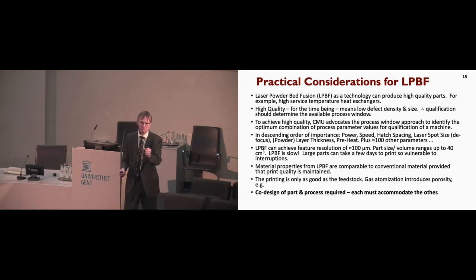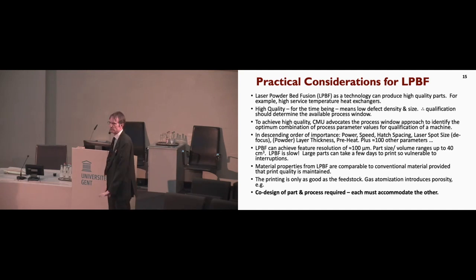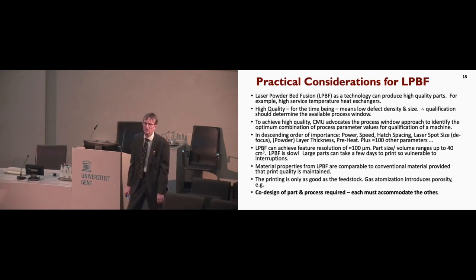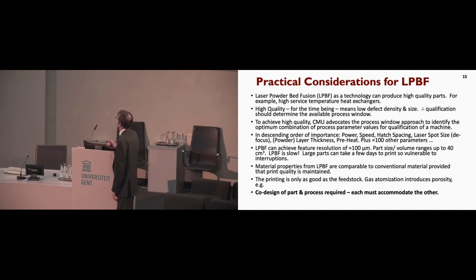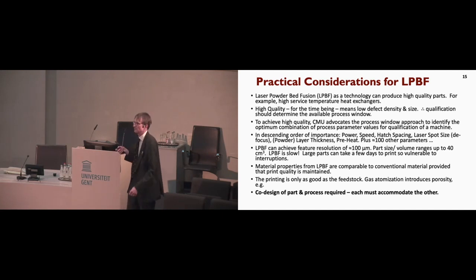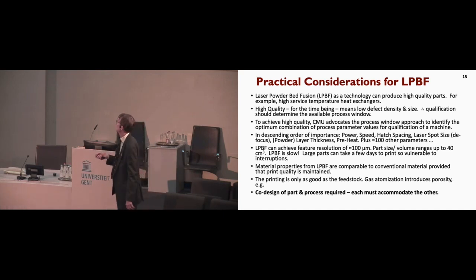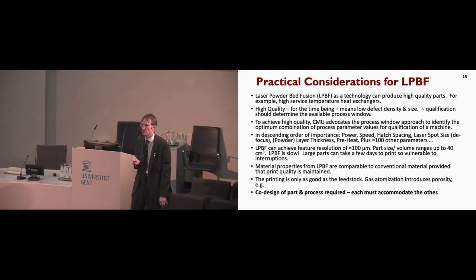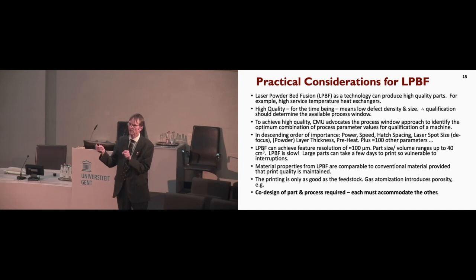Okay, so now I'm going to abruptly change gears, go from low gear to high gear, if you like, and just offer you some more practical thoughts about at least laser powder bed fusion, which at the moment is the dominant technology. It's a technology that basically should be looked at as producing high quality parts. It can do this. And from the perspective of defect content, many of those applications are fatigue sensitive, or maybe they're corrosion sensitive. So the point is, is it possible to print parts with a very low defect density? And my answer is, if you follow the process window approach, if you map out the behavior of your printing process in a suitable space, so at least power versus speed with maybe hatch spacing variations, you can do this.